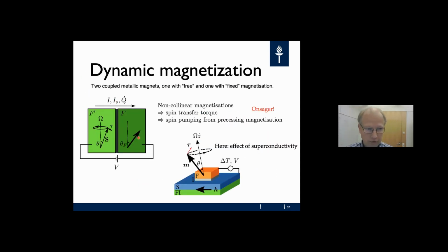So the case of dynamic magnetization is the following. You have two magnets. In one of them, the magnetization can precess around some field, and this precession actually pumps spin into the other ferromagnet. Or if you apply a current through the system, this current applies a spin torque onto this magnetization precession.